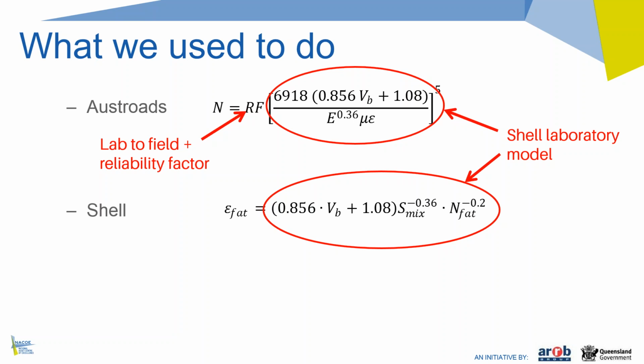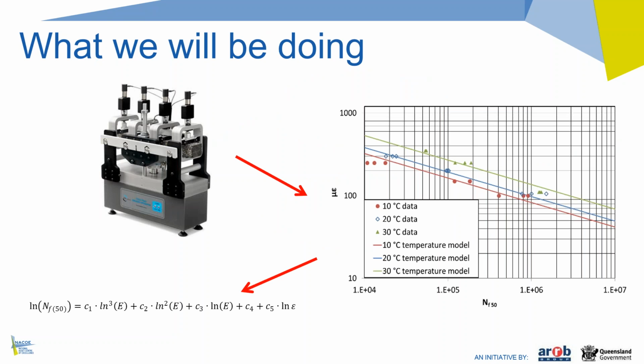Now you could argue that you could replace that general laboratory model, which was developed again on 12 mixes in the 1970s. You could replace that mean laboratory performance model with a mix-specific model and use it in exactly the same way. So that's what we'll be doing, is we'll be running tests in 4-point bending setup. We'll be testing at different temperatures, and then we fit a single model to those tests at different temperatures, and we'll be making the fatigue performance a function of the modulus of the material again, to account for the effective temperature and load frequency.